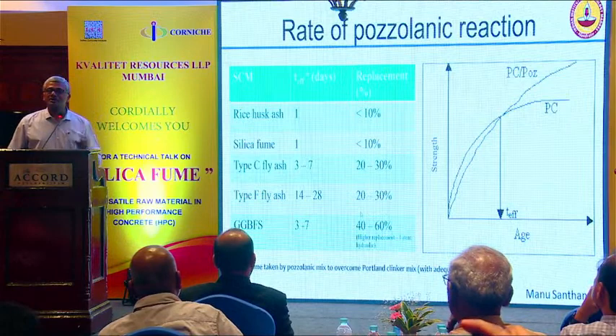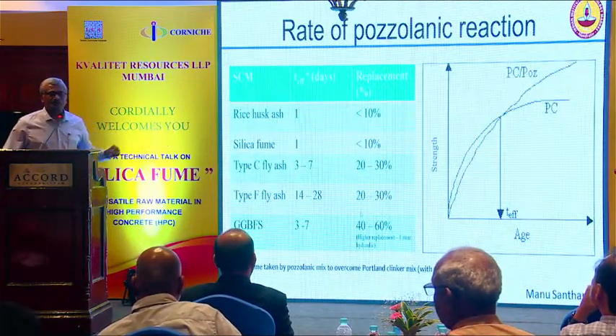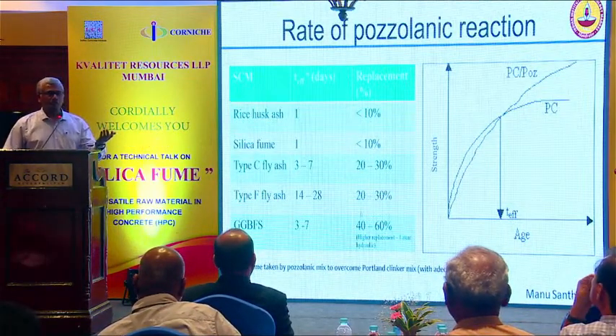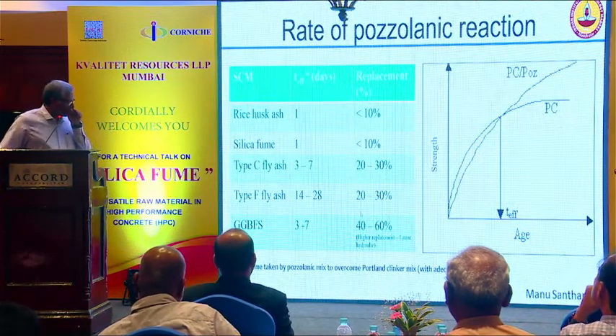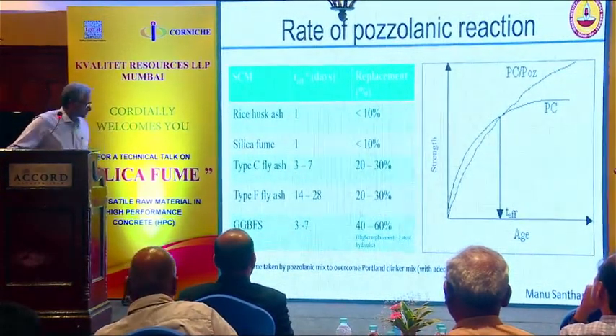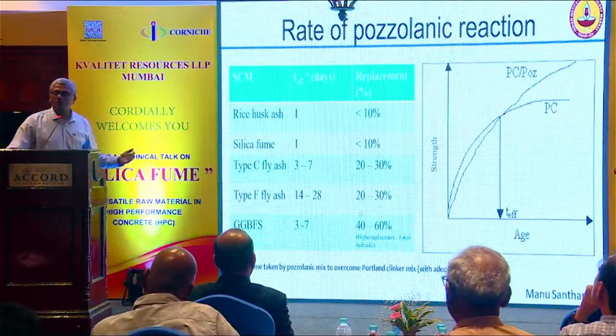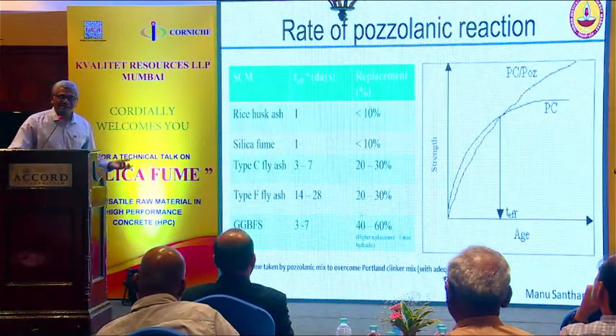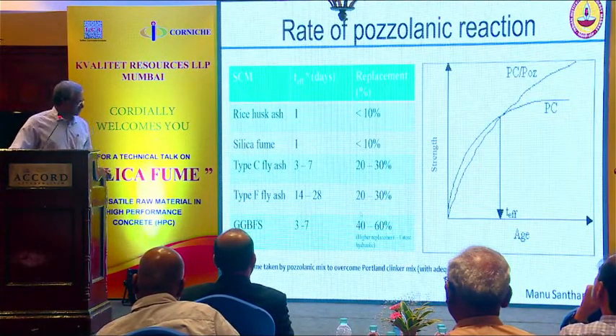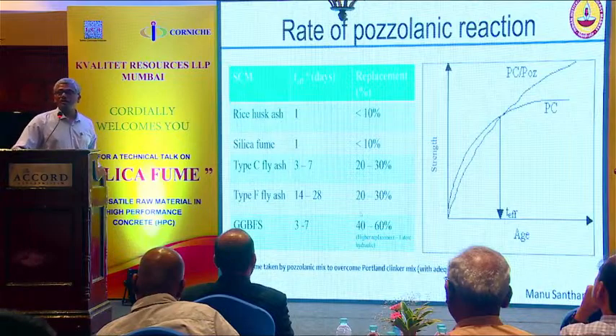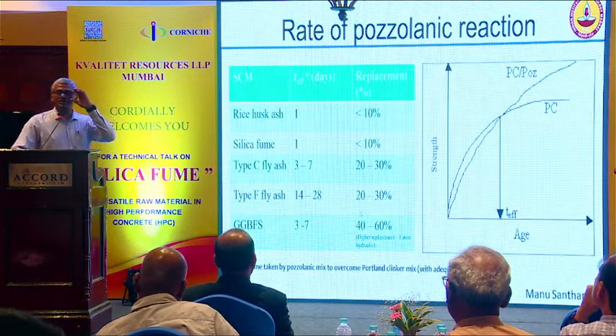So at about 20-30% replacement, it will take about 7 days. So that's why we need to cure pozzolanic concretes for longer time. Type F fly ash will take a bit longer because it's not as reactive, it doesn't have calcium. So it takes about 14 to 28 days to reach equivalent strength that of cement.